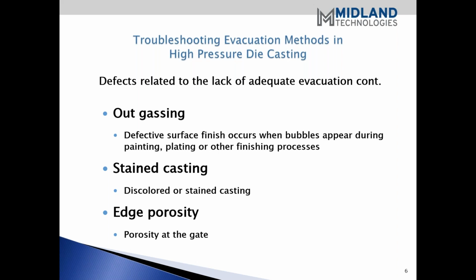And Larry, do you want to fill in more details of these types of things? Sure. Outgassing, of course, if you're in die casting, you're finishing parts. If you finish parts, you're familiar with that condition. It's internal porosity trapped in the casting at the time of solidification, and this porosity is generally closer to the surface of the casting, although the entire casting outgasses over the life of the product. Die casting just doesn't stop outgassing.